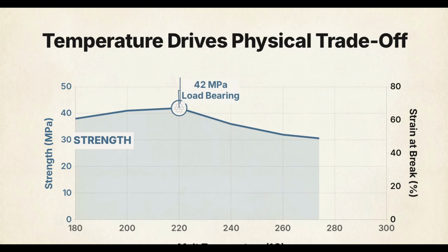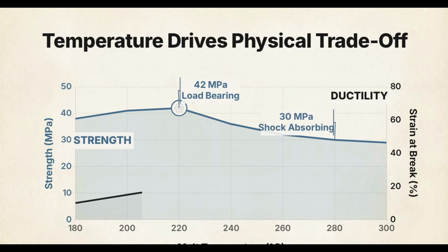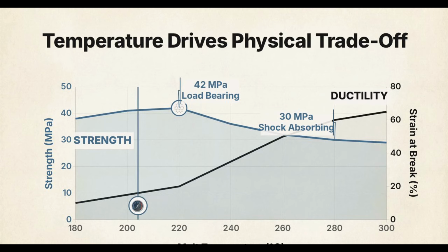stiffness. Pushing the melt temperature above 260 degrees restricts crystallization and increases the amorphous phase of the polymer. The overall strength drops down to this lower peak, near 30 megapascals. However, that drop in raw strength yields a massive gain in ductility. As panel C shows, those same high-temperature specimens stretch up to 60.